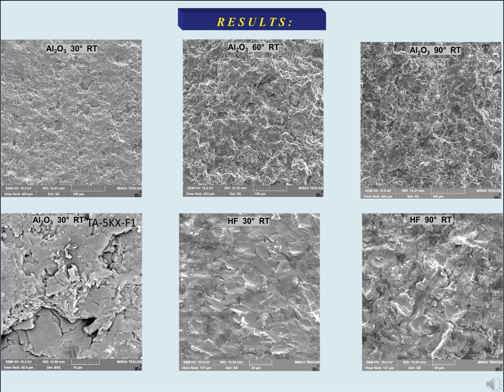In the first three images, the erosive mechanisms are presented for the alumina coating, and they explain the large amount of erosion of the ceramic samples when the impact angle is increased. It can be seen that the scar marks increase as the impact angle increases. In the lower left image is evident the brittleness of the ceramic, showing no plastic deformation and an easy crack formation and propagation. In the last two figures, it's easy to see the plastic deformation for the hard-facing coating, in which the hard carbides and the iron phases make a cermet material with the best results.